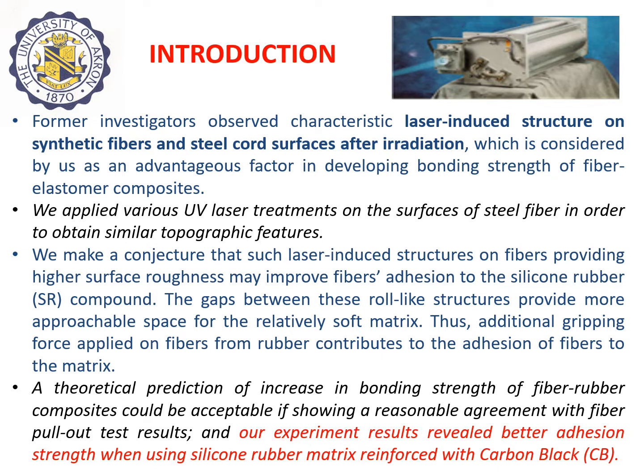We make a conjecture that such laser-induced structures on fibers providing higher surface roughness may improve fibers' adhesion to silicone rubber, and the gaps between these roll-like structures provide more approachable space for the relatively soft matrix material. Thus, additional gripping force applied on the fibers from rubber contributes to the adhesion of fibers to the matrix.